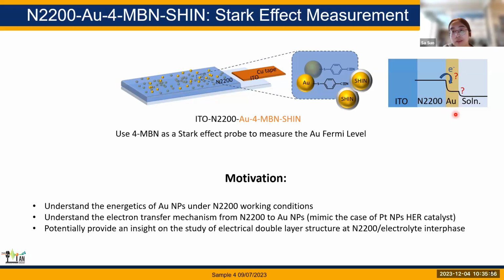Gold here can be a mimic for, for example, platinum catalysts, which use a similar deposition method. But in that case, platinum is a catalyst for HER. It would be very helpful if we can understand the electron transfer from the N2200 to metal sites, for example, the catalyst. And another ambitious motivation, which would be really difficult to do, is whether we can potentially use this method to study the electrical double layer structure at the N2200 electrolyte interface.